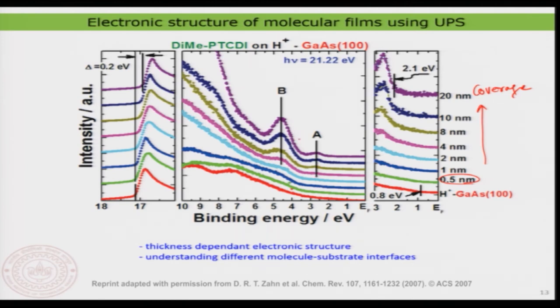So, that is something you also have seen in the case of tunneling spectroscopy, that at the interface there is strong influence of the surface, but as you go thicker and thicker, you basically just start to see the more molecular type structure. But here in UPS, this is much more feasible because this is a technique which is really meant to do that kind of thing compared to tunneling microscope, because tunneling microscope is not very capable of measuring things that are like 20 nanometer thick and so on. It is actually just due to the stability of the instrument and the imaging itself. But here you can clearly do that.